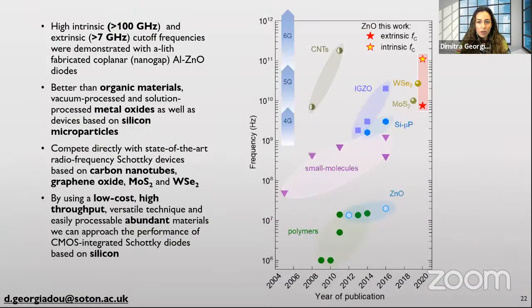So to summarize my talk so far, I have demonstrated solution processed zinc oxide based diodes fabricated with coplanar nanogap electrodes. The undoped and aluminum doped zinc oxide showed high intrinsic cutoff frequencies above 100 gigahertz and extrinsic above 7 gigahertz with the A-lith fabricated coplanar electrodes. And we used inexpensive, easily processable materials, vacuum and solution processed organic materials.